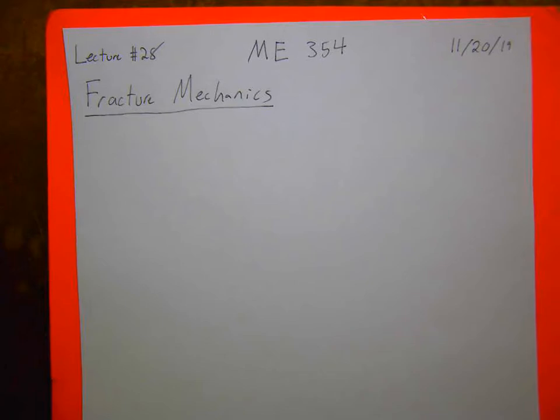Cool. So at the very beginning of class, I think the first day of lecture, I had shown a couple images from the de Havilland Comet. This was one of the first commercial aircraft, and it had a very catastrophic failure, where you can see some of the fatigue cracks that initiated at the corners of these not square but not quite round windows. That idea of stress concentrations, remember it was a factor of 3 for a perfect circle, it's higher for something that's not perfectly circular.